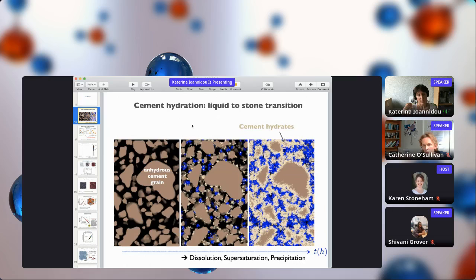Cement hydration is basically a reactive solidification. We start with a liquid suspension, with cement grains at the scale of microns and water. These grains start to dissolve, and once the solution is supersaturated with calcium and silicate ions, we have precipitation of cement hydrates, or calcium silicate hydrates, that grow around the grains and eventually fill up the space. So we have a dissolution-precipitation process that turns a liquid material into a stone.